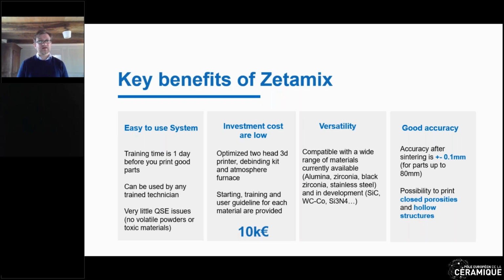The last thing is it has a relatively good accuracy. I'm saying relatively because obviously if you compare with SLA, for instance, SLA has a better accuracy. I'm not denying it, but the accuracy should be around plus minus 0.1 millimeter, and that is on relatively big parts, up to 80, 100 millimeter. Obviously, it's also, as any 3D printing technology, interesting in terms of making complex parts, hollowed out structures, very low volume production, and so on. The key benefits I was stressing are mainly compared to other technologies.